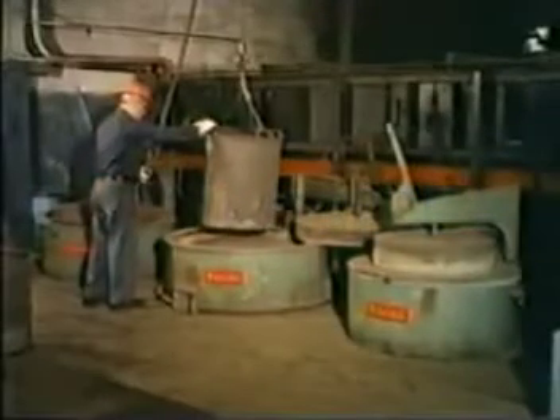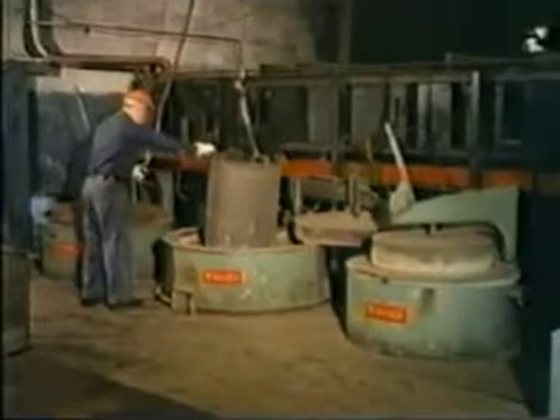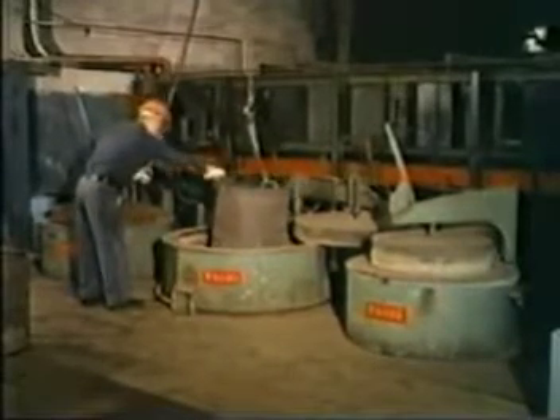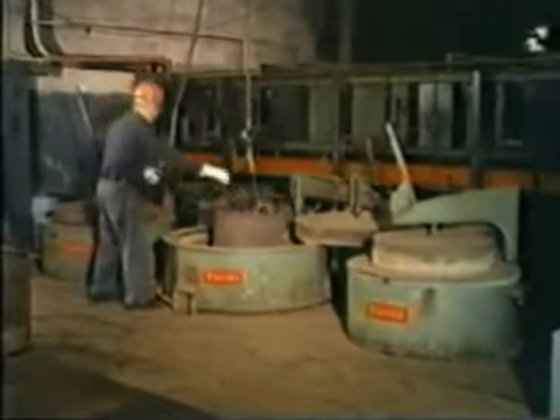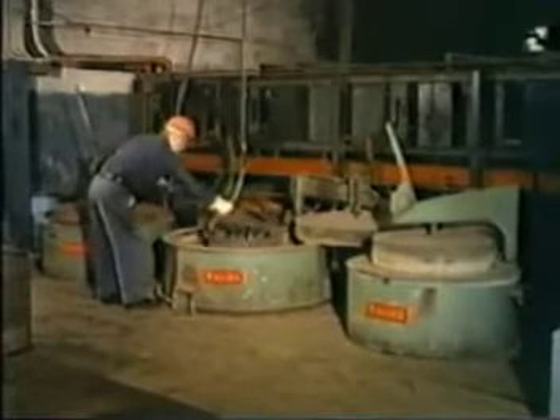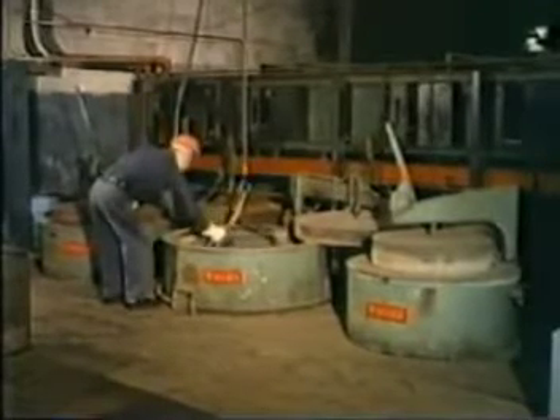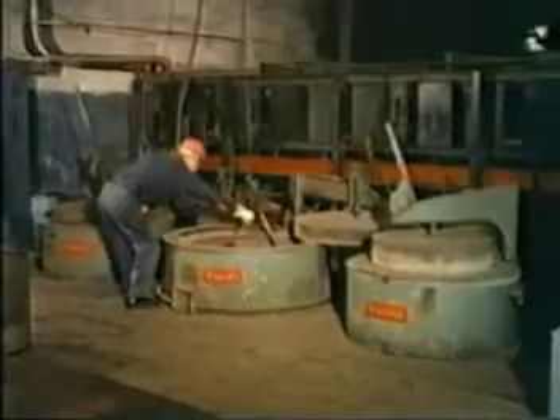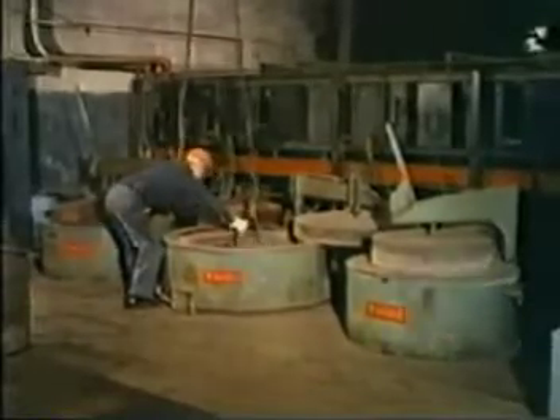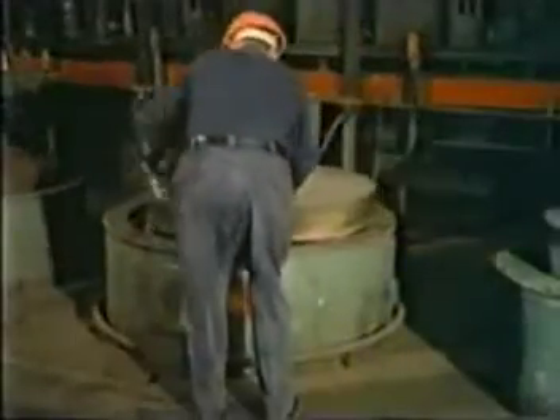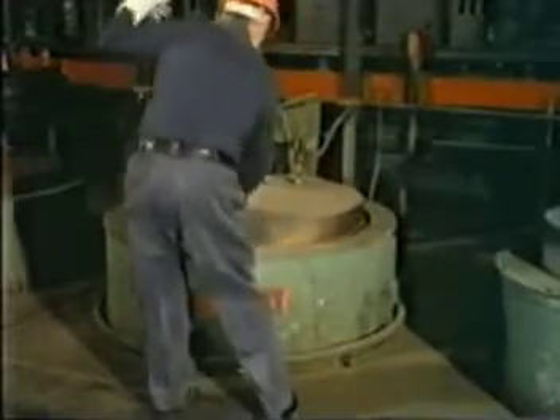Tempering. After steel has been properly heated and quenched to obtain maximum hardness, it is highly stressed and is too brittle to be of practical use. To eliminate this condition, the steel must be reheated at a temperature lower than that used for hardening. This reduces the brittleness and makes the material usable.